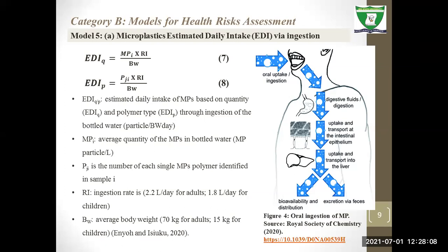So we can see the MPI is the average quantity of microplastic in the water, times RI. RI is the ingestion rate, which is estimated as 2.2 liters per day for adults and 1.8 liters per day for children, divided by the body weight of the adults or children. For adults, average body weight is 70 kilograms, maybe for people in Nigeria, then 15 kilograms for children. So this data might vary for different countries. We can use this to estimate the daily intake of microplastic.